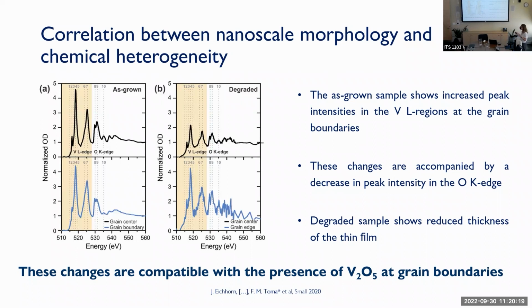But what you can extract from this spectra is that at grain boundaries, you have a phase segregation of vanadium oxide. And this phase segregation of vanadium oxide is the one that can lead to the corrosion. Vanadium oxide is more soluble. And by being more soluble and by phase segregating at grain boundaries, then it can leave the material and basically generate that corrosion that I showed you earlier.